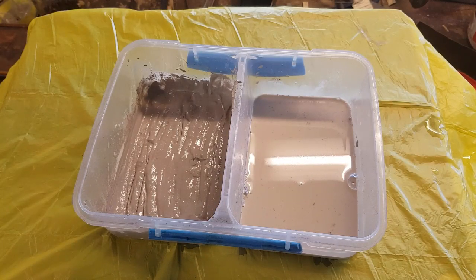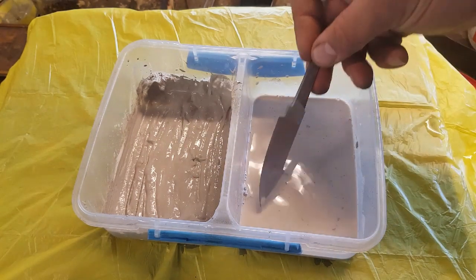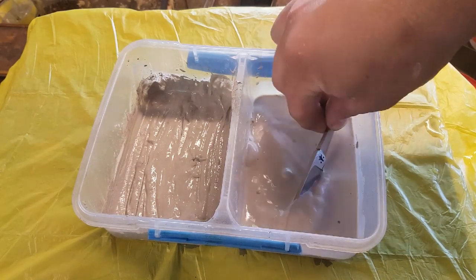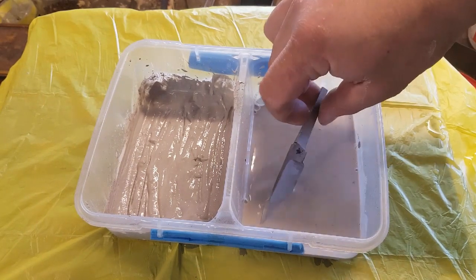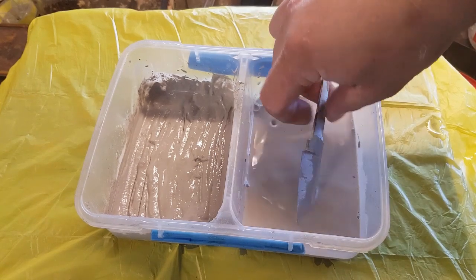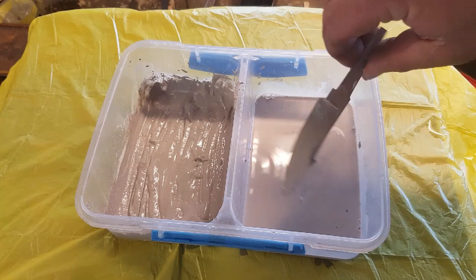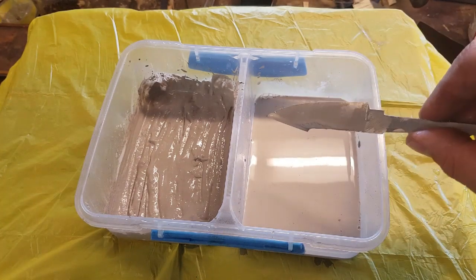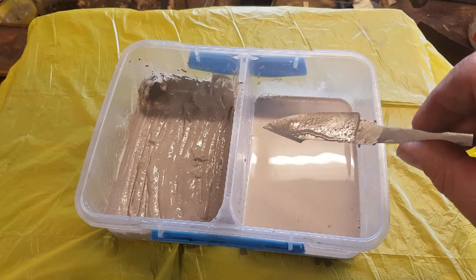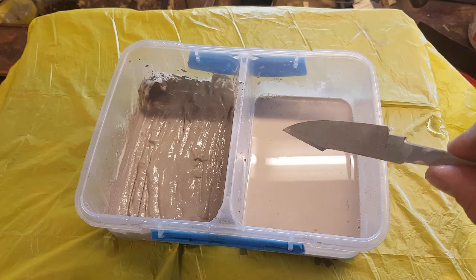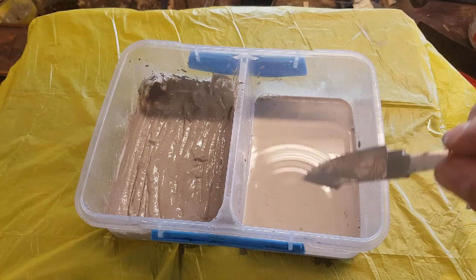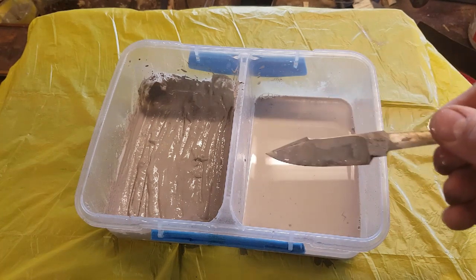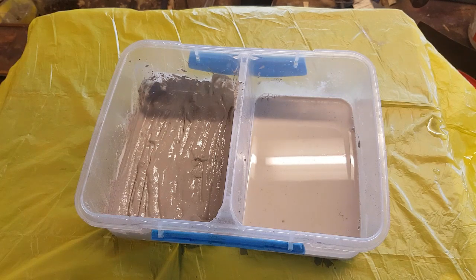So now that I have my 2 clay mixes, my first step is going to be to soak this in the light mix. I want a consistent coating, an even consistent coating of the light clay mix all over the surface of this blade. Now, one thing you'll notice is that the clay is clinging to some spots and not to others. And I did this on purpose because there are some oils from my hands and from the grinder and stuff like that on the blade that are not allowing this to stick. So what I'm going to do is hit this quickly with some acetone or some degreaser, and then I'll come back and show you how it changes.